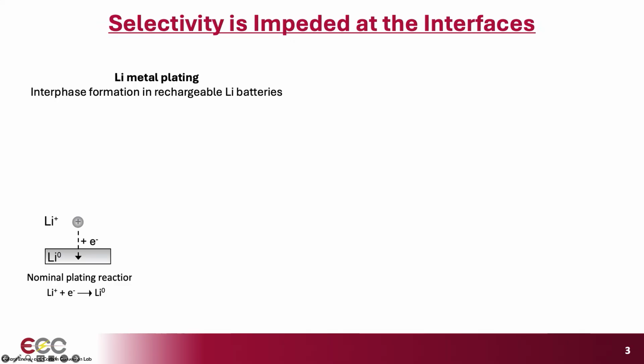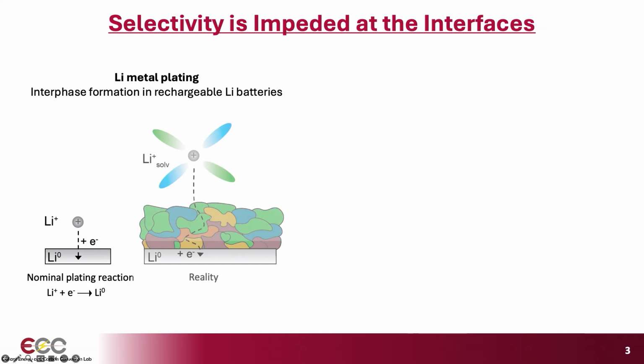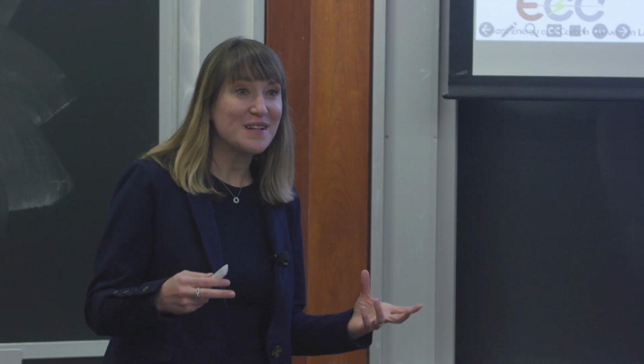Taking batteries as an example, if you look at a lithium metal plating reaction, as you would have in a lithium metal battery, on paper it's relatively simple. You transfer an electron to a lithium ion to form lithium metal at the interface. What could go wrong? But in practice, it's quite a lot more complex than that, involving the participation of partially desolvated lithium ions that react and decompose to form a derived passivation layer that strands lithium irreversibly in this layer and leads to cycling inefficiency. I'll be talking a lot more about that in my talk today.